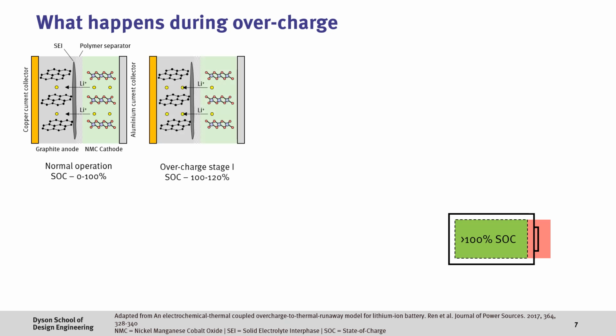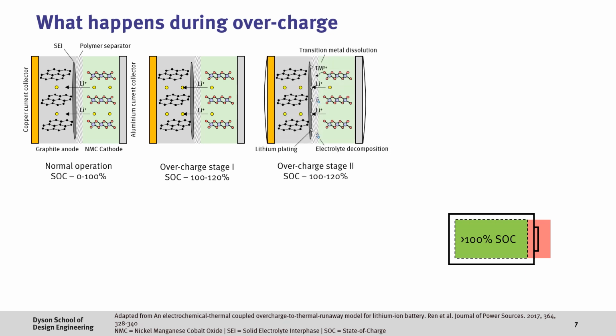Now, in reality, there's excess lithium in a battery that allows for a small amount of overcharging, though this normally results in reduced lifetime. Eventually, the graphite anode is no longer able to hold all the lithium, and some is instead plated on the anode, which can form dendrites that can short circuit the battery.